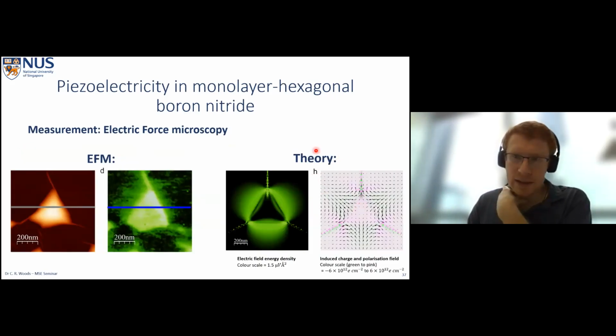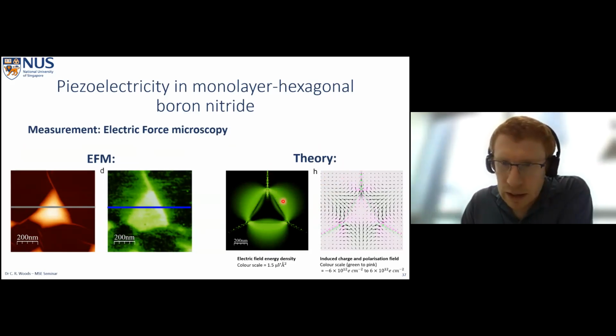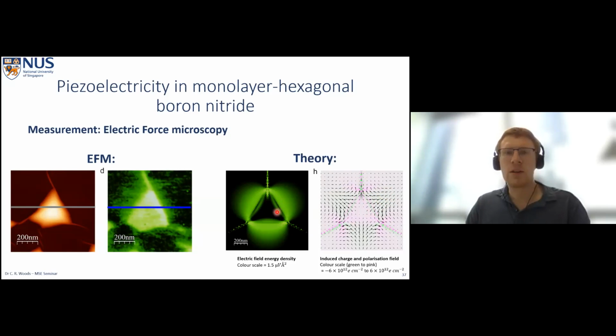We can compare this to theoretical calculations. We can look at the shape of these bubbles and plug them into our calculations and measure the electric field energy density as a function of the radial distance from the bubble. We can look at the polarization field and the induced charge sign, and we see good correlation between what we see and what we expect to see from our theory.